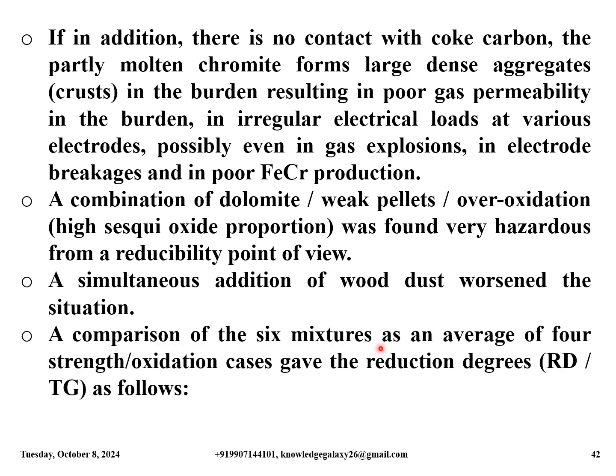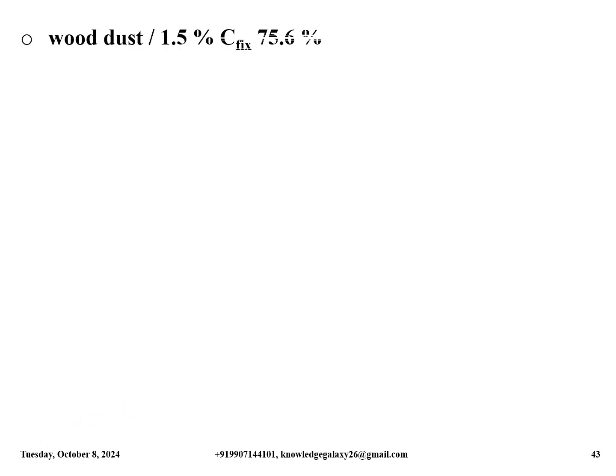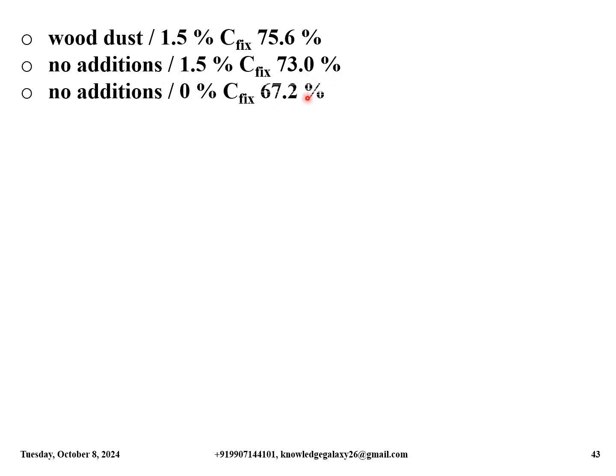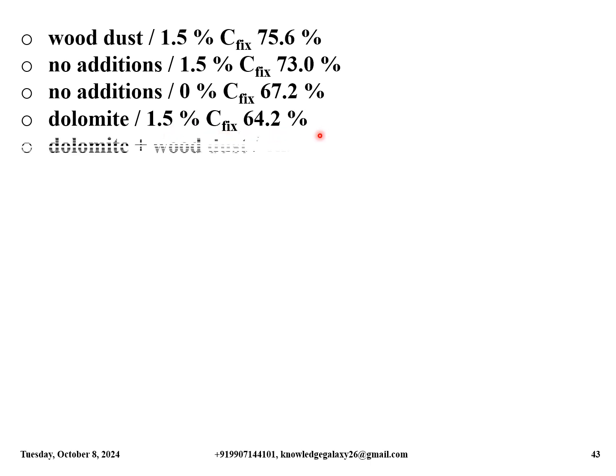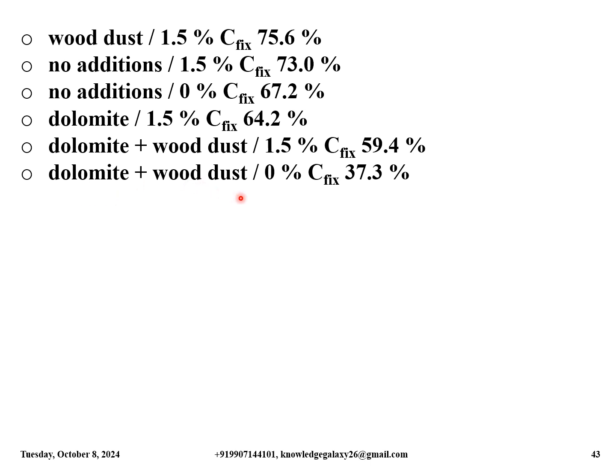A comparison of the six mixtures as an average of four strength and oxidation cases gave the reduction degree RD as follows. Wood dust 1.5% C fix, that is having 75.6%. No additions 1.5% C fix, 73%. No additions with 0% C fix, 67.2%. Dolomite with 1.5% C fix, 64.2%. Dolomite plus wood dust and 1.5% C fix, 59.4%. Dolomite plus wood dust and 0% C fix, 37.3%.